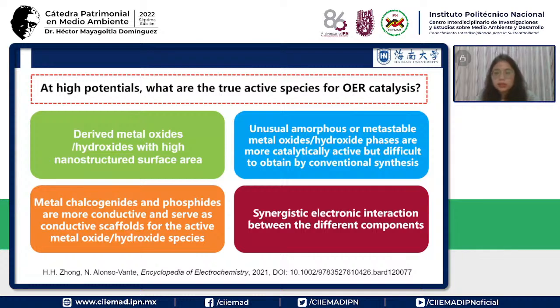And the second one is that on the surface, unusual metal oxide or hydroxide phases are more catalytically active, but they are difficult to obtain by conventional synthesis. That means by conventional synthesis, we cannot get this kind of unusual or non-stable metal oxide or hydroxide phase on the surface. But during the OER process, you get these materials, and then they are more catalytically active.